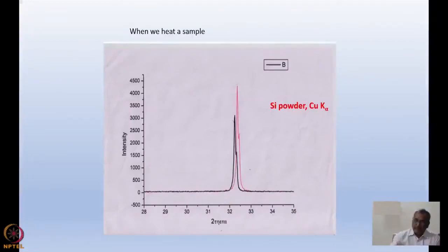You have the Debye-Waller factor reducing the intensity of the lattice, and the expansion of the lattice causes shifting of the peak. You might have also noticed that there is a small hump here. That is related to instrumental resolution. Actually, copper has two alpha lines, K alpha 1 and K alpha 2, and also K beta. This is splitting of the two lines in the experiment. This is an experimental result which really demonstrates that your Debye-Waller factor takes care of the thermal effect.